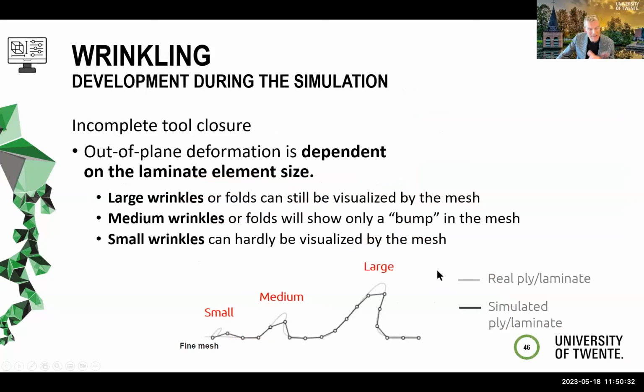The nice thing about these simulations is that we can see what the laminate is doing during the deformation, during the forming process. And at incomplete tool closure, we can have a look at whether waviness or buckling regions arise. So in the actual laminate, you'll have the gray line over here, and if the elements are large enough, the elements will simply follow the large buckles. The smaller these wrinkles become, the harder it becomes to represent them with the elements. So this one is definitely sub-element level. It's very hard to represent in the actual simulation.